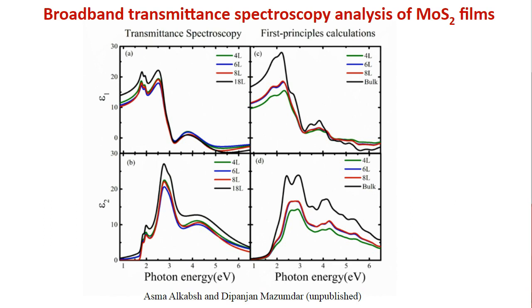And also, we see pretty good reasonable agreement in the scaling behavior. What do you mean by that? That means that the dielectric constant of 18 layers is higher than the dielectric constant of 4 and 5 layers. Sometimes, as trivial as it might sound, it is not very easy to show it because of strong interference from the substrate. So we have to carefully eliminate the substrate effect here to show the right scaling behavior.